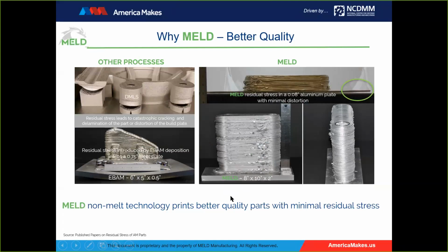And in fact, we did a project a couple of years ago where we incrementally reduced the plate thickness to see when we would observe residual stress, and we got down to 0.08 of an inch, a very thin plate, finally showing signs of residual stress with a little uptick on the outside part of the plate. Again, don't want to oversell this. We're a solid state technology. We don't melt the material, so you should expect low residual stress, but there's some visual verification of that.